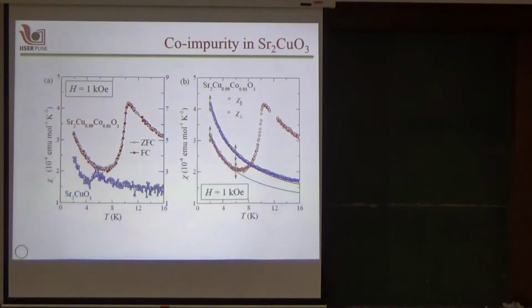So now we come to the story of cobalt. When we dope cobalt, just 1% of cobalt in the system. So this is the pristine compound where the ordering happens at 5.5 K. With cobalt doping, the ordering temperature has enhanced to almost 10 Kelvin.